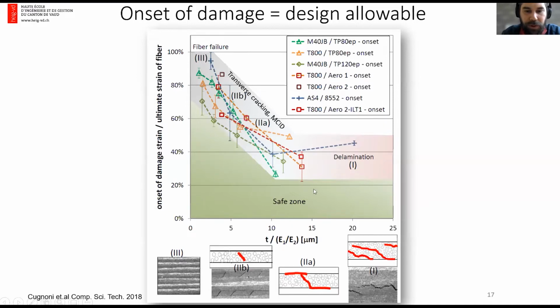So if we look here for the thick ply region, which is here around 300 micrometer plies, the behavior is dominated by delamination, and the safe zone for use of a composite is about 30% max of the ultimate strain of the fiber. While for the intermediate ply thickness here, we have a combination of transverse cracking and matrix cracking induced delamination, and the safe zone reaches about 50% of the fiber ultimate strain. So it means we can use half of the potential of the fiber.